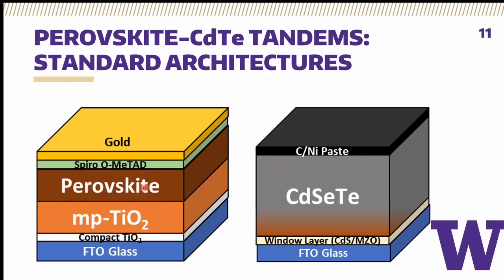Perovskite cells don't have to have this architecture, and in fact, most of the tandem architectures aren't quite like this, but nonetheless, perovskites usually adopt some sort of pin architecture with an N-type contact layer transporting electrons away from the device after they're photoexcited. In this case, that's TiO2. A P-type organic transport layer, in this case spiro-OMeTAD, shuttles away holes from the perovskite, where holes are just basically electronic states where an electron should be and isn't because the electron got excited by light. And that's the perovskite junction, with metal contacts on top and bottom.